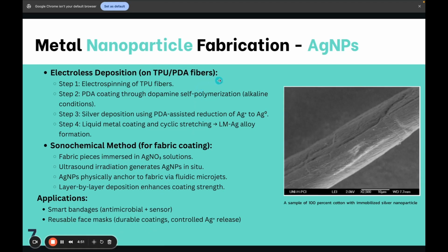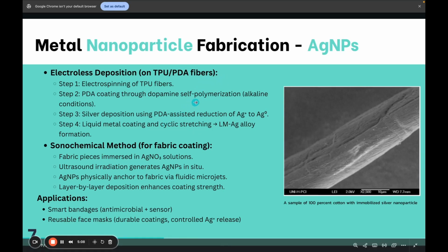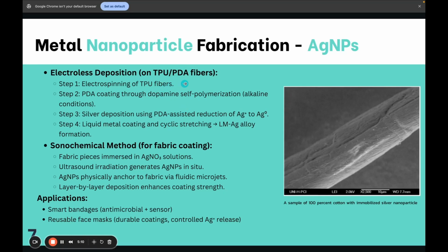So the first method that we have here is the electroless deposition. In electroless deposition, the first step is the electrospinning of TPU fibers. Electrospinning is a technique to create nanofiber mats from polymer solutions using a high voltage electric field. A thermoplastic polyurethane solution is pushed through a needle, where high voltage causes fibers to stretch and collect on a grounded collector. The result is a porous nanostructured fiber mat, which is ideal for surface modifications.